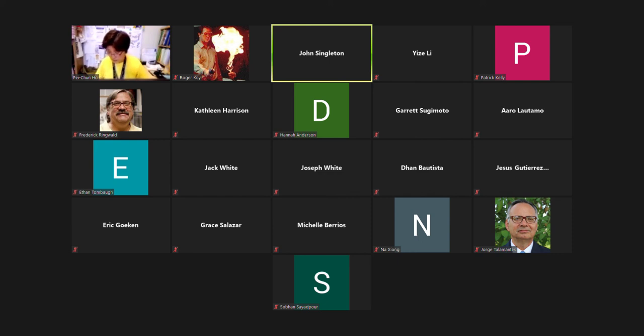So the reason it got christened strange metals is that a lot of the pnictides and cuprates and some of the ruthenates show this linear temperature dependence. Initially this model by Sachdev's group was to explain that. What you have to have is some reservoir for the fermions not to contribute to the conductivity.